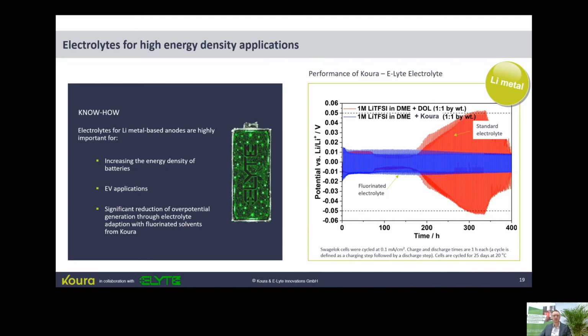So what we are performing here, we did lithium stripping and plating in a 3-electrode setup, and we monitored the evolution of the overpotential. And the reference electrolyte is well known to the community. So this is a mixture of a linear and a cyclic ether. And you can see that the increase in overpotentials starting at maybe 200 hours here in red is very dramatic. And by changing the cyclic ether to a Koura compound, we can drastically improve this. And some recent results also show that this combination is very suitable for lithium sulfur cells.